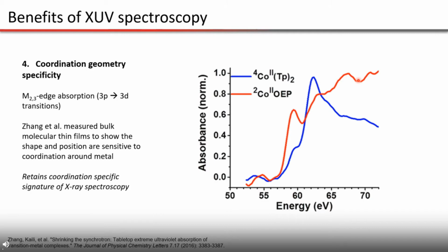However, if we compare two different states of a similar sample that have different valence bonding, what we would find is that the excitation from a core level into that valence state will be adjusted based on how the external orbitals are participating in bonding, how they might be hybridized, how they might be minimized in energy in terms of stabilization or destabilization because of the external ligand field. So this is all extracted with XUV spectroscopy as well.